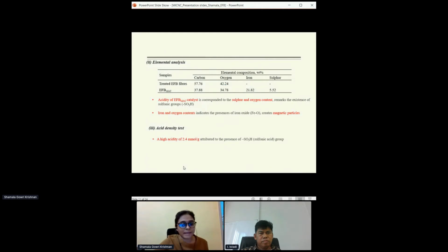Continuing to the EDX analysis, the treated fiber has a high composition of oxygen and carbon, while the presence of iron and sulfur in the catalyst shows that the fiber has been successfully impregnated. The presence of sulfur and oxygen indicates the acidity of the catalyst, while the presence of iron and oxygen indicates magnetic properties. With this, the catalyst achieved an acidity of 2.4 millimole per gram, which indicates the presence of sulfonic group.